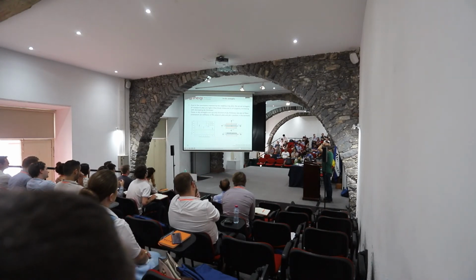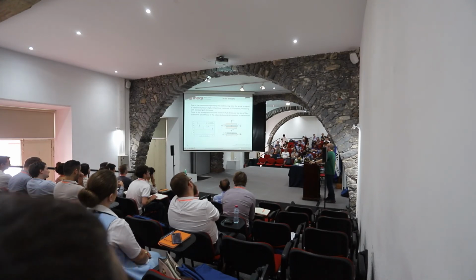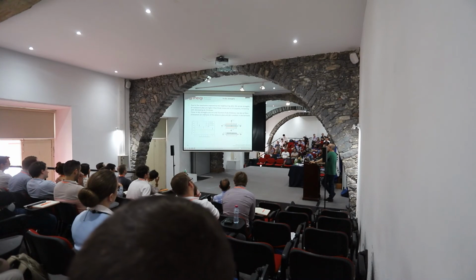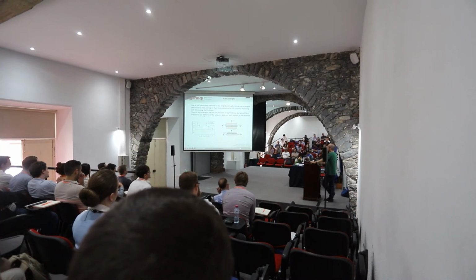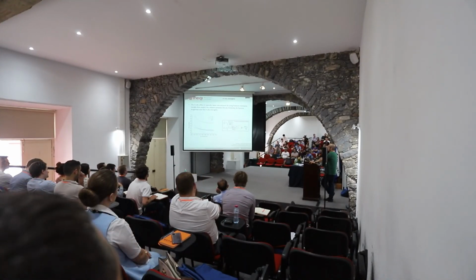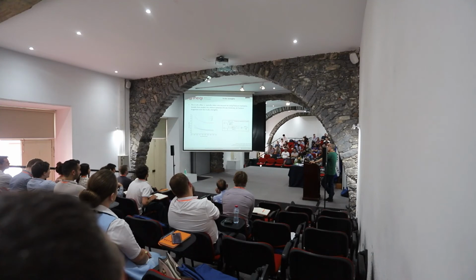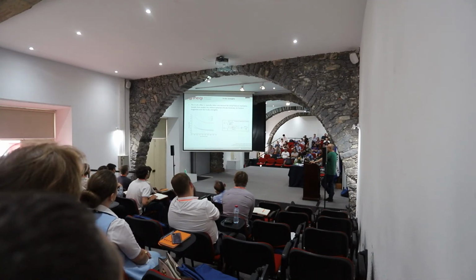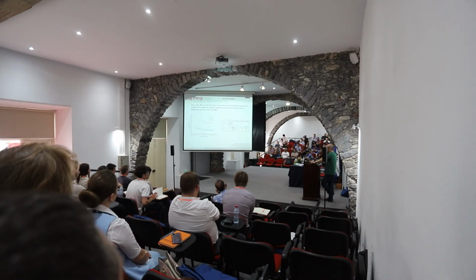So these in situ strengths, it's important to note, are not only a function of the ply thickness, but also of the fiber orientation or stiffness of the adjacent plies, okay? I'm not going to go into details of how the models were derived, but in our opinion it's a fracture mechanics problem that we solved using fracture mechanics models.